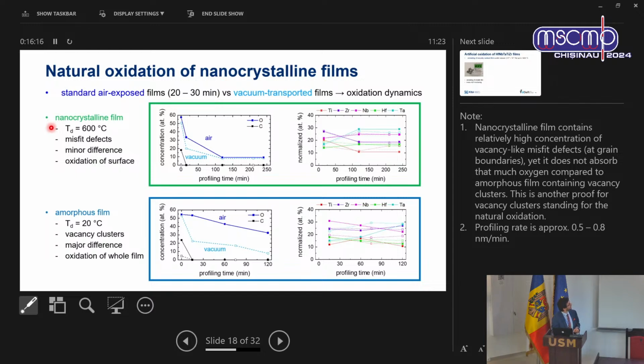And the results are well visible here. You can see that the nanocrystalline film, yes, it oxidizes on air, but the difference is negligible compared to the results for the amorphous film. So really, by controlling and removing those vacancy clusters, you can make your films resistant to the ambient oxidation.